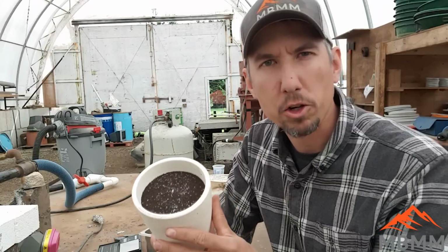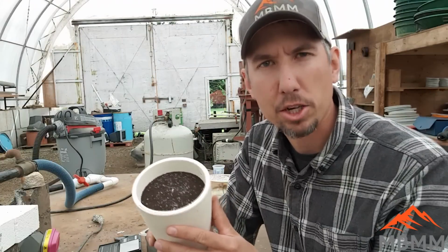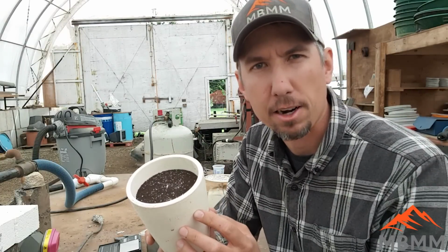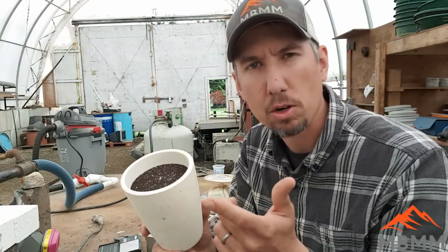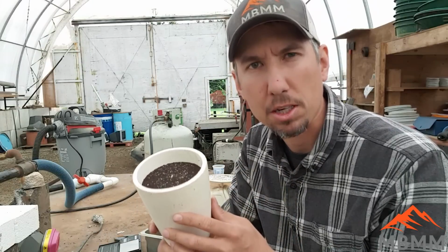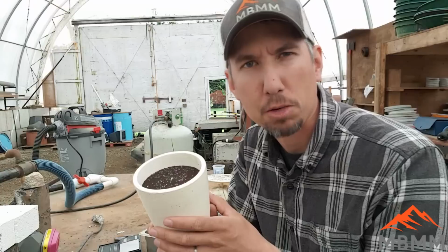All right, here's our number 5 crucible. We got it filled up. I got 200 grams of the matte in here, 200 grams of borax, 200 grams of lye, and 100 grams of silica sand. That's our standard kind of flux recipe that I've been using.